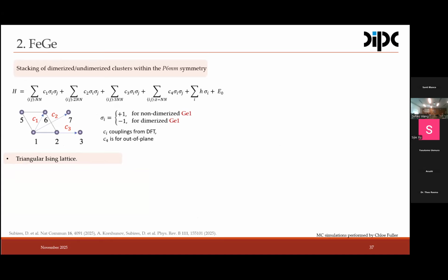So as I said before at the beginning of this chapter, below the charge order transition, the trigonal germanium atoms dimerize and form pairs of dimer and non-dimer pairs along the z-axis. So we make a toy model stacking dimerized and undimerized clusters in a triangular lattice. I mean, there is one position, one corner of the lattice, where we cannot put dimer or non-dimer, as the system is highly frustrated, right?